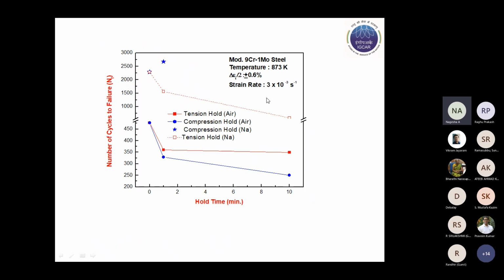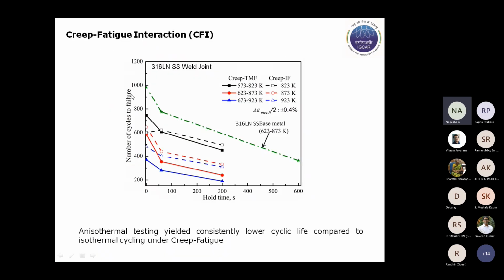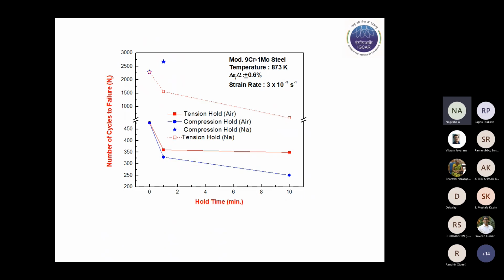A corollary can be drawn from our earlier tests which were conducted in the liquid sodium environment, wherein in air we have seen, in isothermal creep-fatigue interaction tests which were carried out earlier, this is not related to TMF, but since it has a connection with the present results I've just shown, that in air compressive hold time gave rise to a lower cyclic life, whereas the compressive hold showed a higher life when tests were done in sodium.